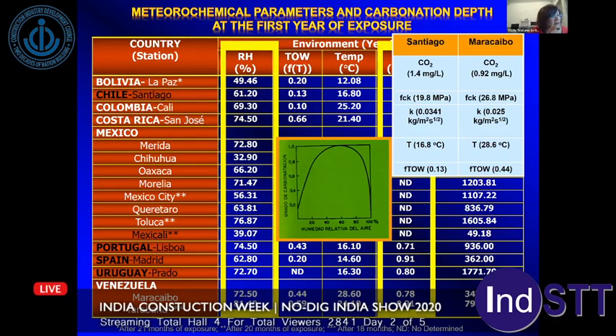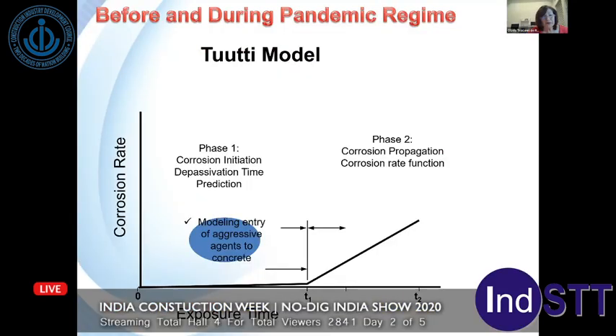The figure shows the Tuutti model, where we are working in both phases. Phase 1, during corrosion initiation, the depassivation time prediction, especially for urban and rural environment, where we just have one station where the rebar is activated. But in the marine environment, we are working now in phase 1 and also in phase 2 because we have enough information to model both of these regions.